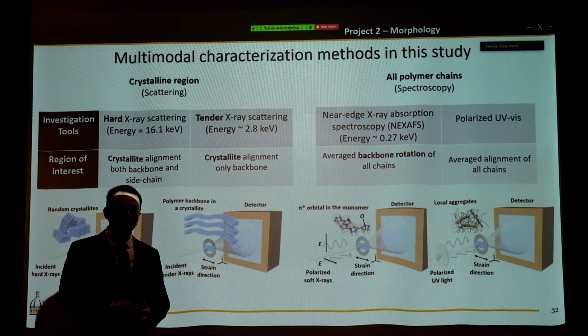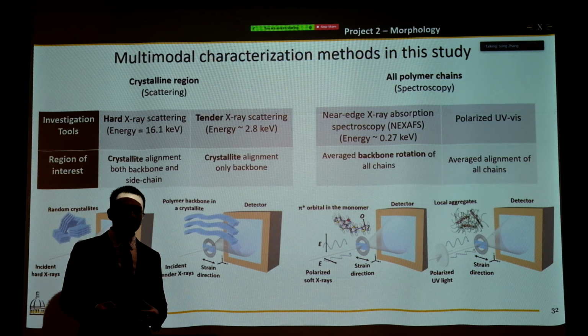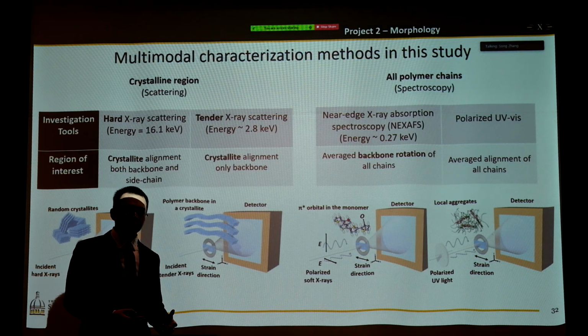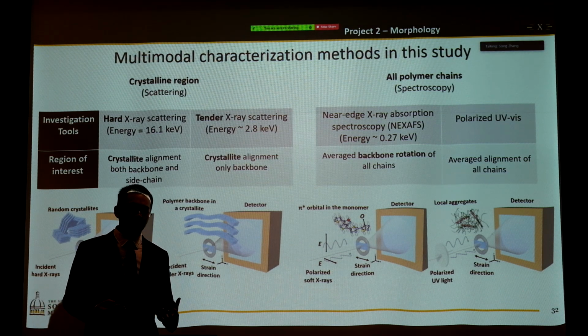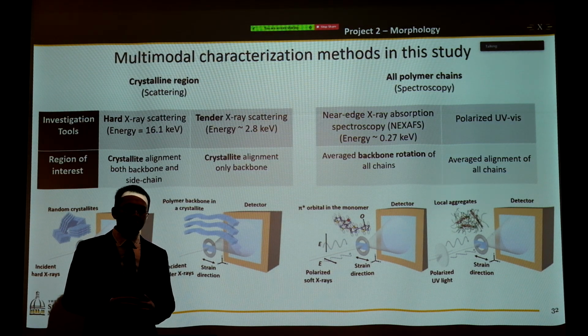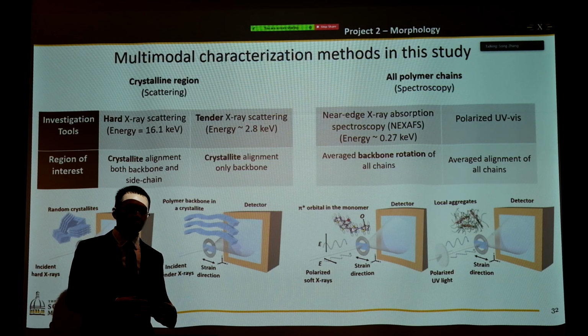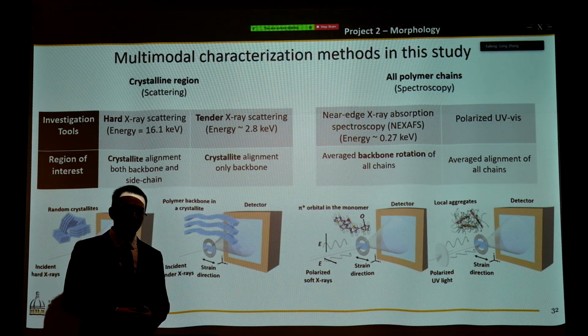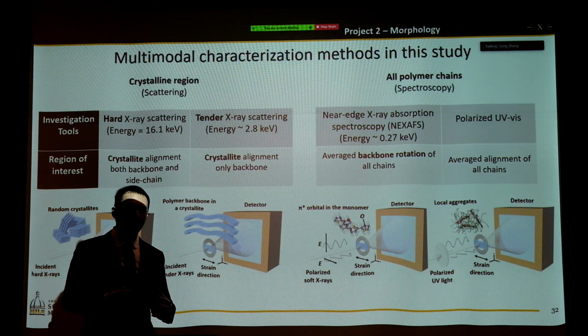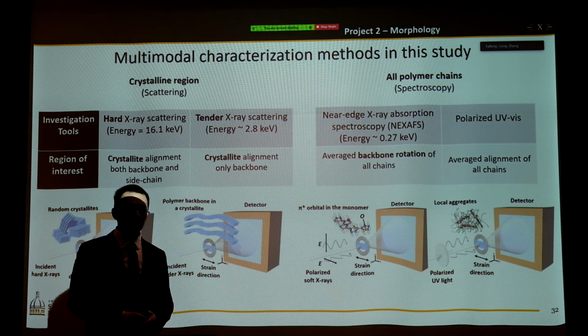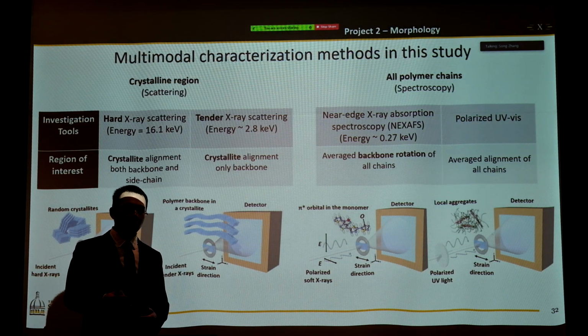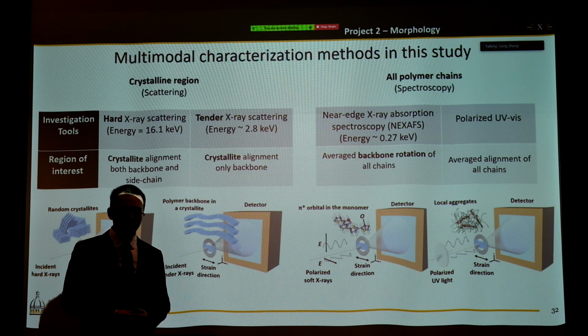Next, by using spectroscopy technique, which does not only look at the crystalline domain, but also at the amorphous domain. So next, NEXAFS, or near-edge X-ray absorption fine structure spectroscopy, provides a method which, by using a polarized soft X-ray, we can see the backbone rotation during the chain alignment.